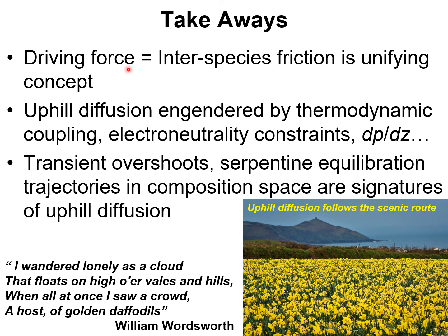The most convenient formulation for diffusion is the Maxwell-Stefan formulation, in which the driving force acting on a species is balanced by friction which the species experiences with partner species and with the pore wall of membranes.